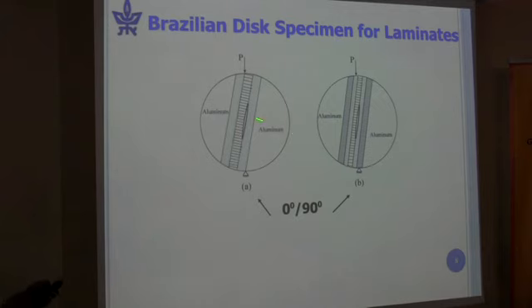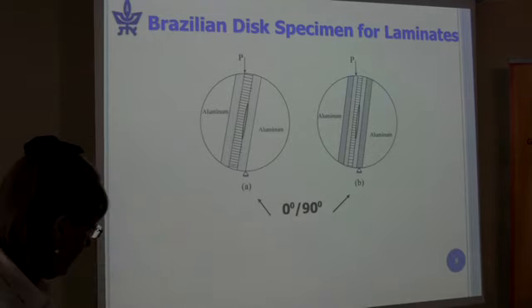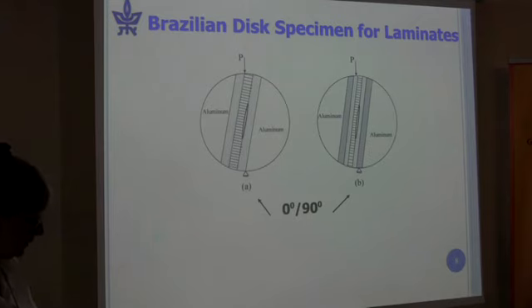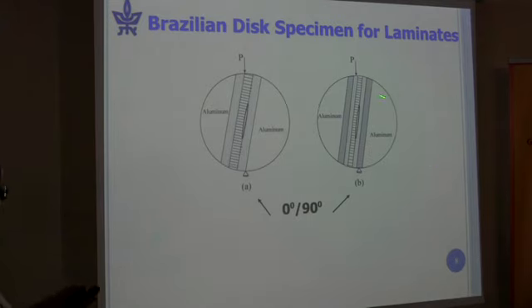It's about 40 millimeters in diameter, and this particular one has fibers in the 0 degree direction, fibers coming out at you in the 90 degree direction, and fibers in the 0 degree direction. The composite strip is about 12 millimeters in width. And this is another layer. Here we have, again, 0, 90, 0. And we have stiffening composite layers so that the plate that was made wouldn't bend. And when we carry out the analyses, we model it all. And we place these aluminum discs to get a circular specimen, because for handling, if we only tried to load this composite strip, we would have a lot of difficulty.